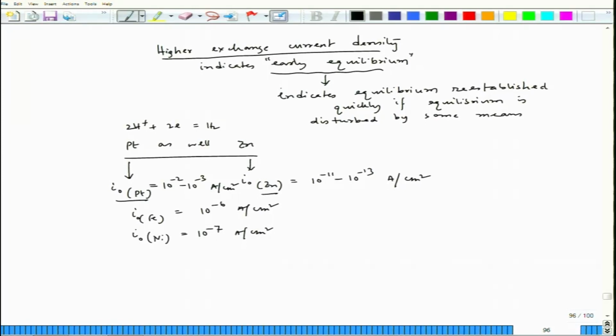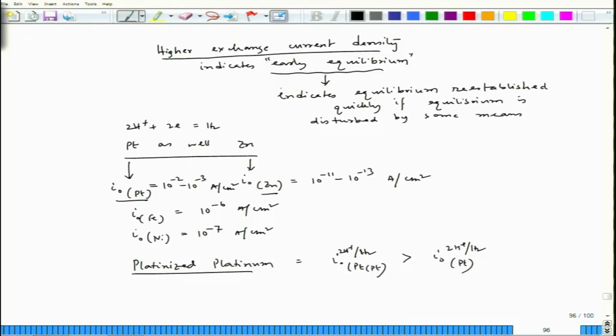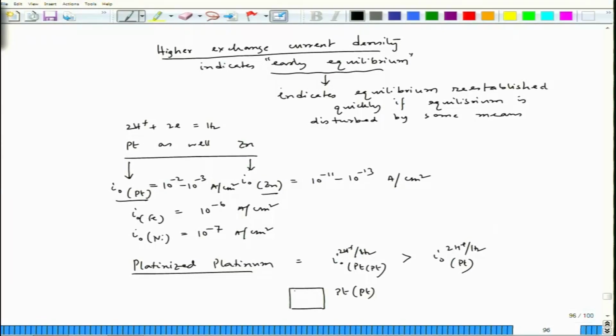Now, instead sometimes we use platinized platinum, and in case of platinized platinum, I0 for this hydrogen reaction is much higher than I0 on platinum. See, when it is platinized, on platinum, platinum is plated. So, when platinum is plated, it actually forms a very rough surface, and it means that if we have a particular area of platinum, and if it is platinized platinum, then the actual area increases. If we see this from the cross section, it would look like this. So, this is the cross section from the side. So, actual area increases,